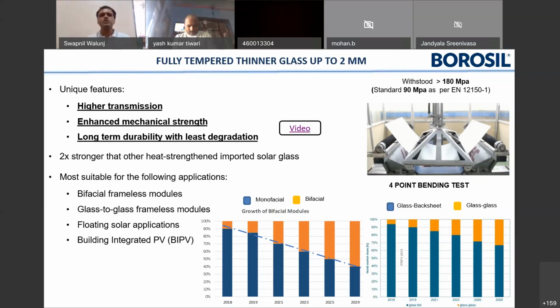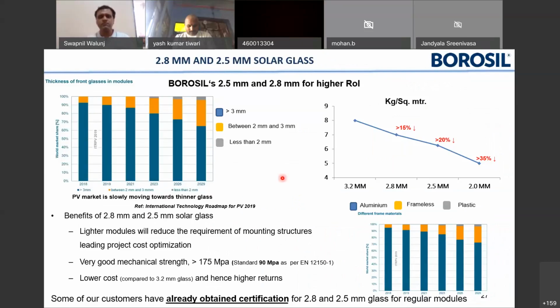So we'll come to this 2.8 and 2.5 mm solar glass. Again, I would like to refer to this ITRPV. If you see the glass which is thicker than 3 mm, it is going to be the most penetrating glass. But the other glass, which is between 2 and 3 mm, which is 2.5 and 2.8 mm, is going to see a rapid rise in utilization. And you can also see glass thinner than 2 mm coming into the picture after 2023.